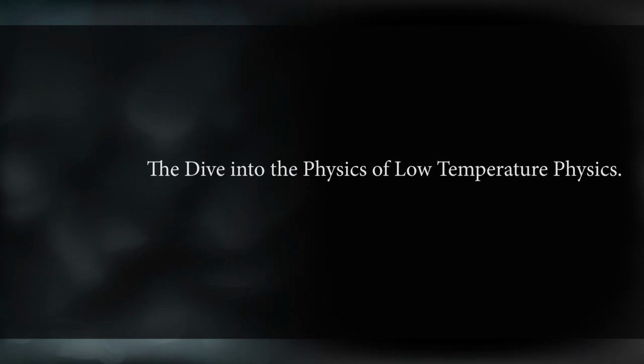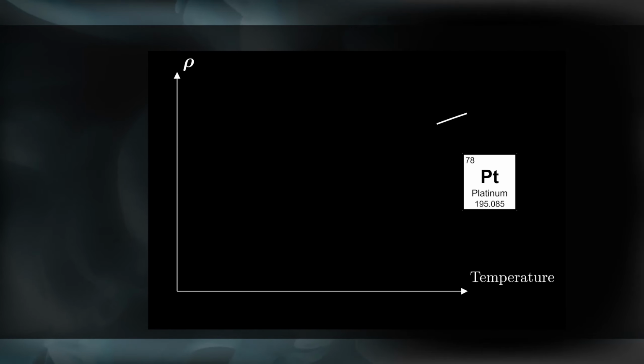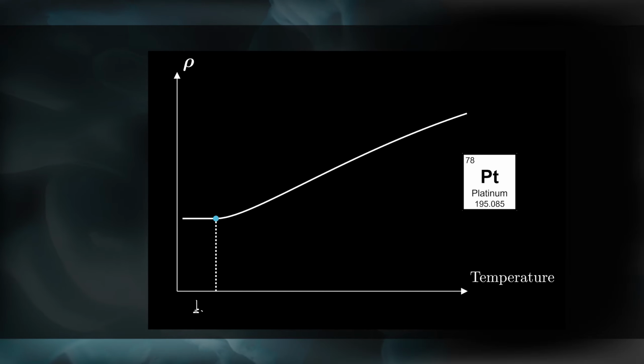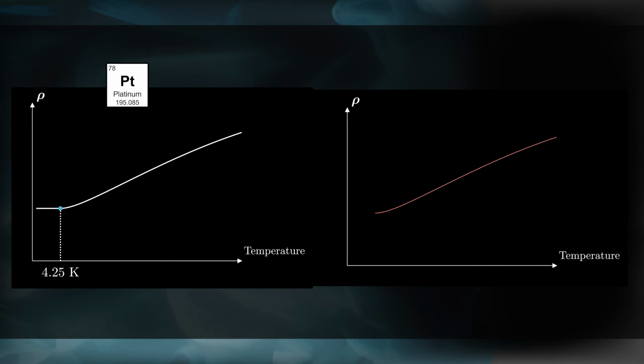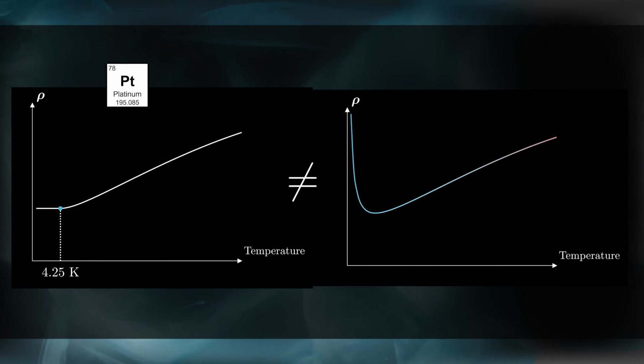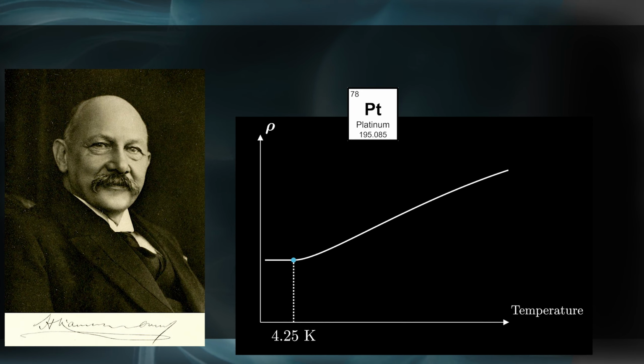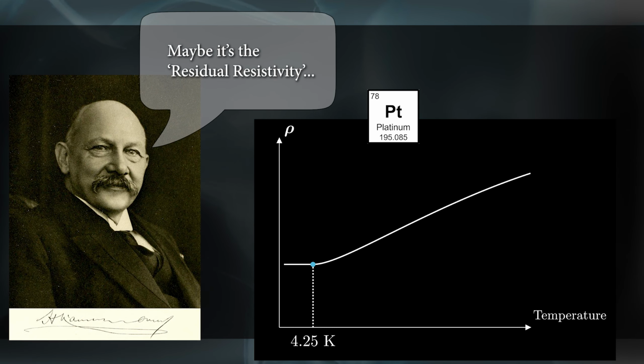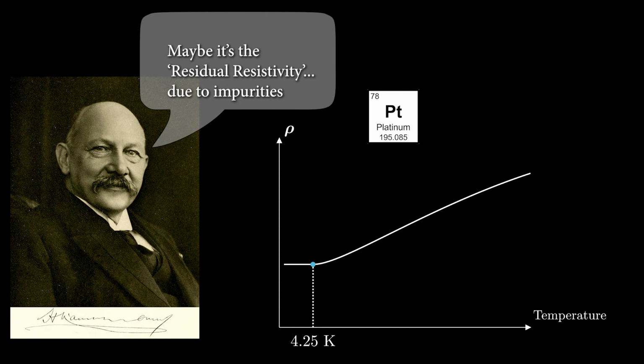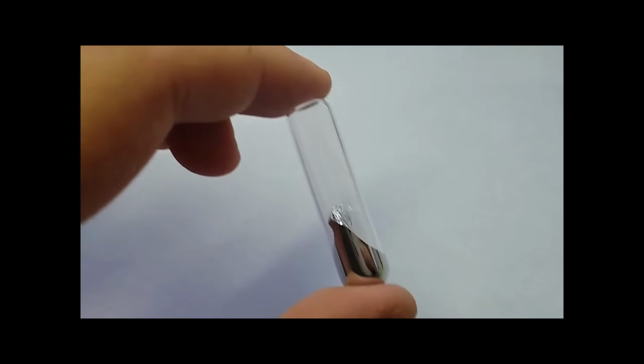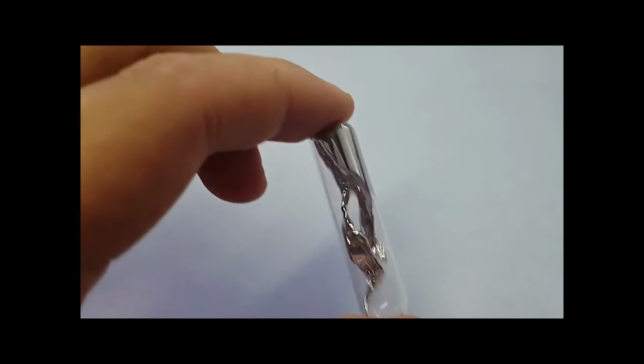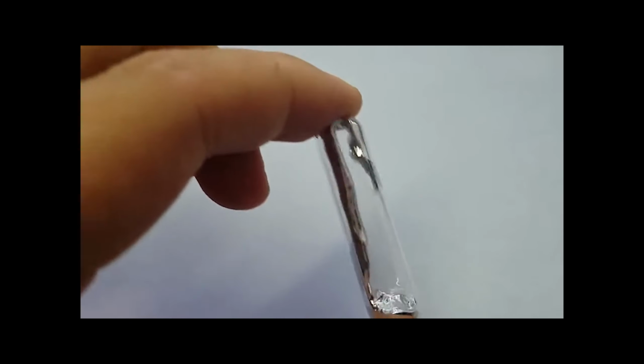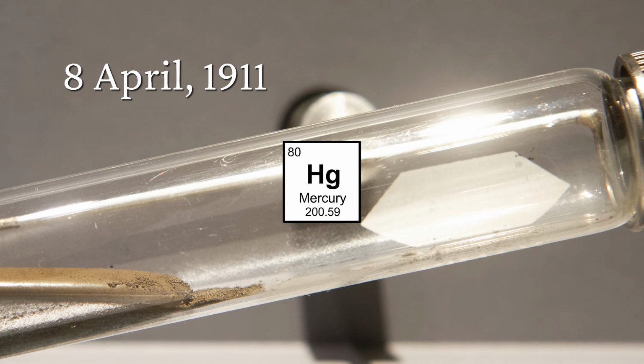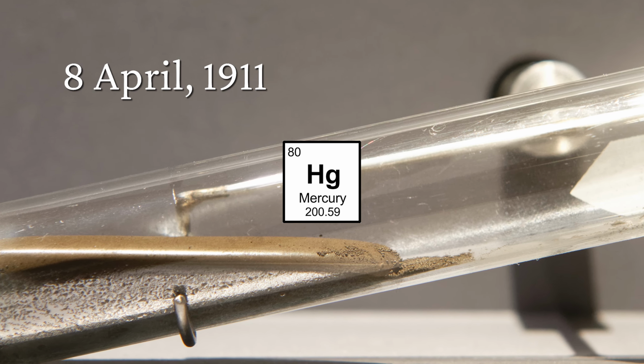Onnes measured the resistivity of platinum at these extremely low temperatures. And what was observed was that the resistance of a platinum wire became constant below 4.25 Kelvin. This ruled out Lord Kelvin's theory, as he had predicted a minimum value and then a sudden increase instead of a constant resistivity. Onnes supposedly thought that the resistivity had fallen to a residual value that depended on the purity of the sample. And the Leiden lab had a lot of experience with purification of mercury. And since liquid mercury in a capillary simply freezes at negative 39 degrees Celsius, contaminations due to drawing of thin wires could be avoided. On 8 April 1911, the measurement of resistivity of mercury at liquid helium temperatures would take place.